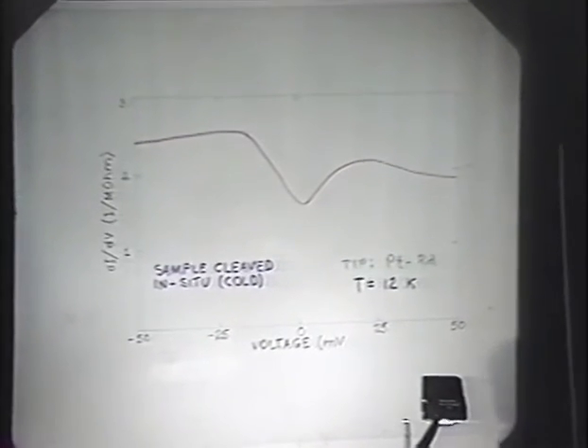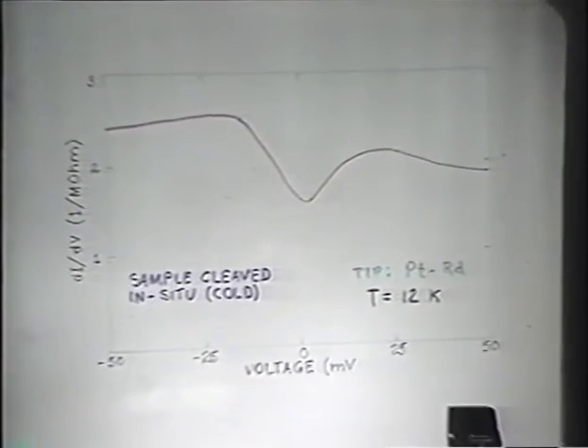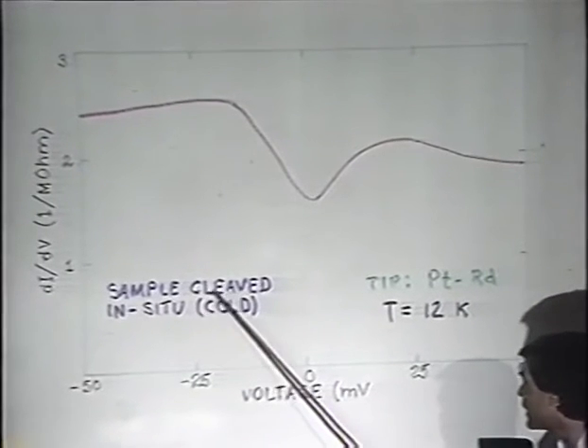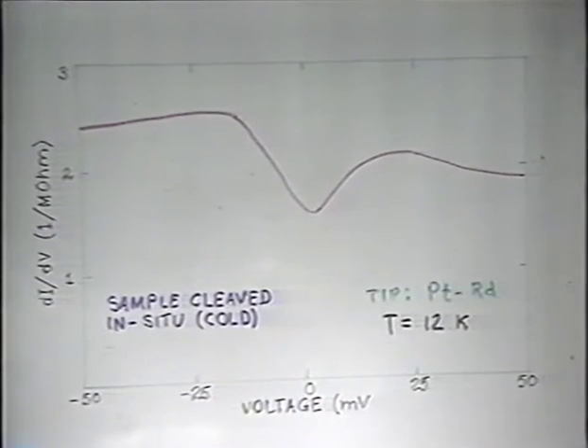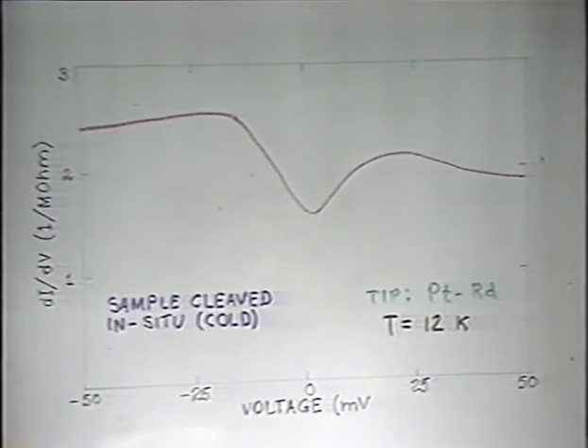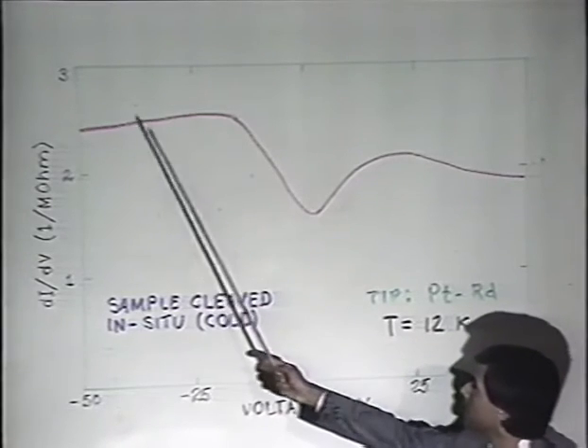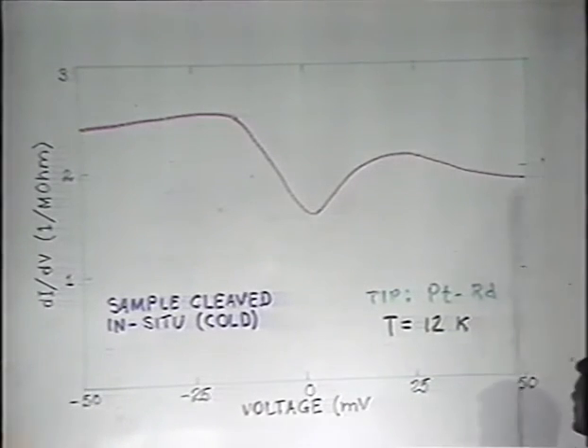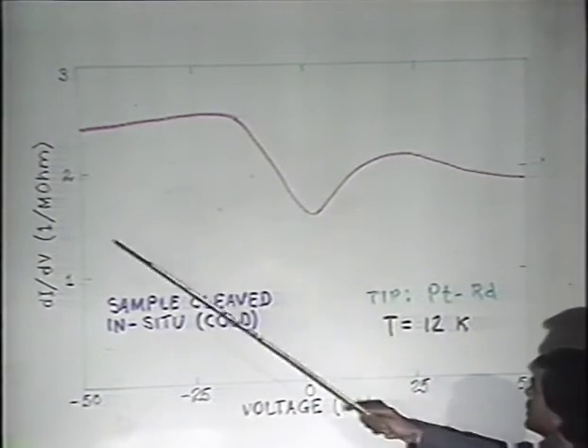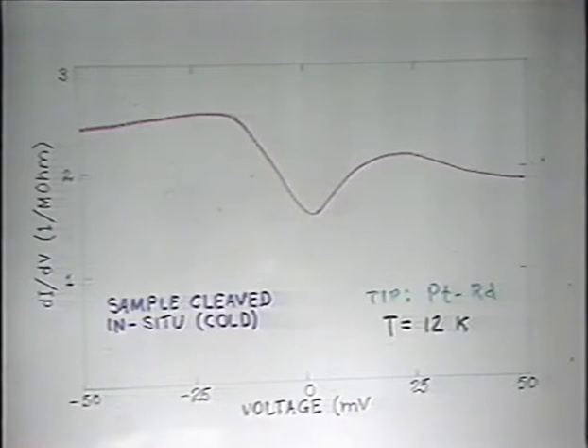As I mentioned, if we get a clean surface, the background curvature that everybody's seeing is gone. And in this case, we have cleaved the sample in situ while it's cold in order to not lose oxygen in the vacuum. Again, the temperature is 12 Kelvin. As you can see, the parabolic curvature in the previous data is completely gone. The asymmetry is still there.